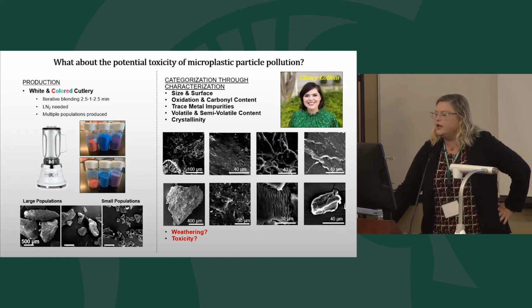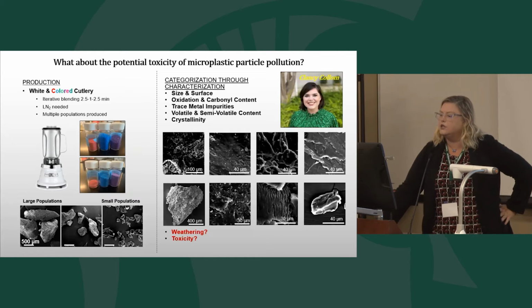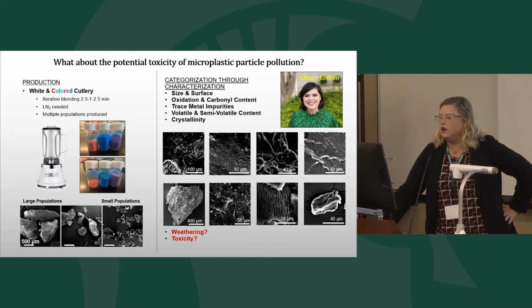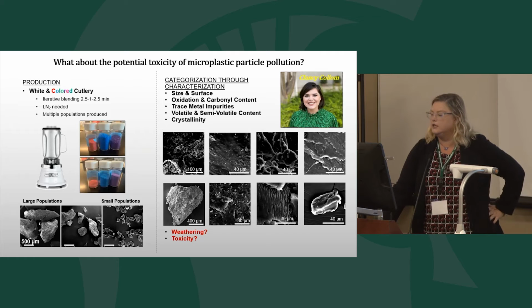The categorization that we're using is done through size and the surface properties, oxidation and the carbonyl content, which I'll talk about data sets from each of these in a minute, and trace metal impurities. A lot of the colored plastics will have some sort of metal doping in them. Sometimes it's pigmentary chemicals, organic chemicals, but sometimes they're metals that produce the different colors. Then what the volatile and semi-volatile content may be, and then crystallinity.